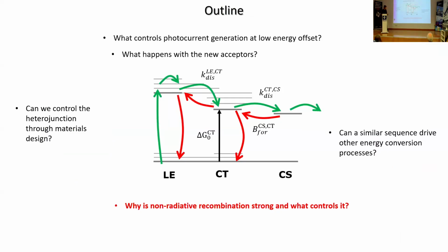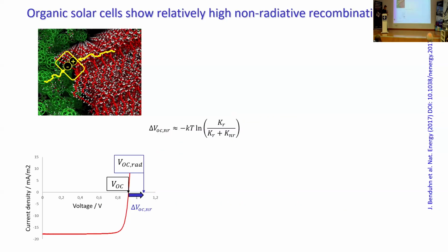So I'm going to start with the question about recombination and what limits it. With the solar cell, you want to generate a current and a potential at the same time. And the maximum that potential can be when you illuminate your solar cell with what we call a standard sun is the open circuit voltage. And that open circuit voltage will be limited by the band gap of the material that you use, and also by the ability of that material to convert the photoexcitations into current. And if there's an efficient loss pathway where charges are recombining through defects or whatever, then the voltage is limited. And so the size of the voltage is a reflection not only of the band gap, but of the strength of the recombination processes in the material.